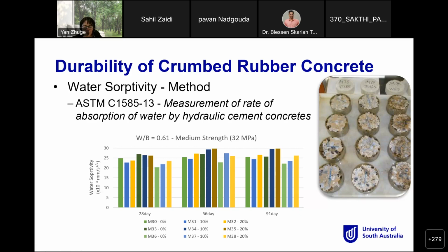But this does not really occur for the 56 day test, where the water sorptivity for mix M37, that is 10% rubber, is higher than M38, which is 20% rubber. So this is a big inconsistent result for this, the blue color, but all others follow the same trend where you have higher rubber contents and the water sorptivity was a little bit higher. But even having said all this, we can see there is no significant difference in water sorptivity compared to the control sample, even at 91 days.